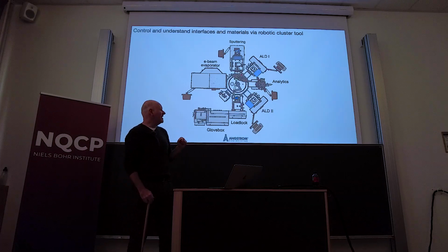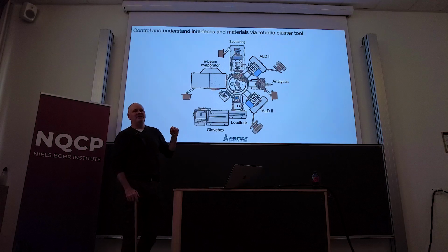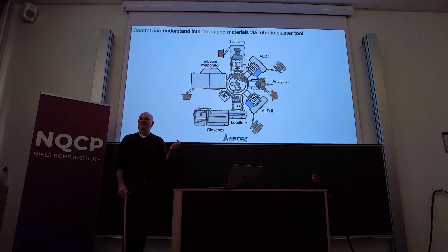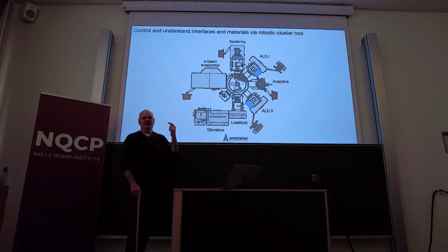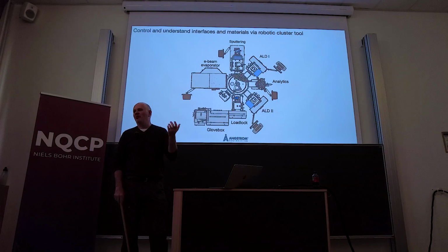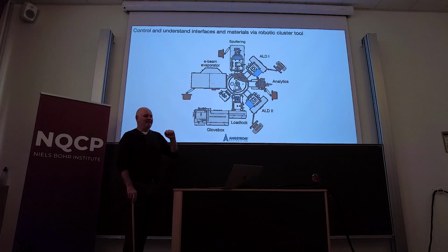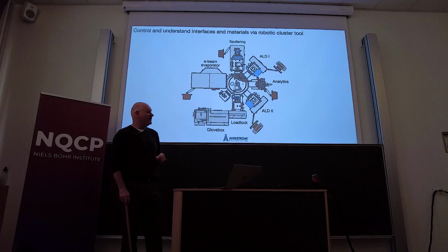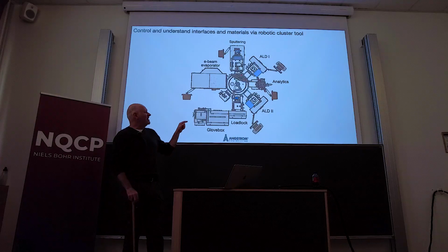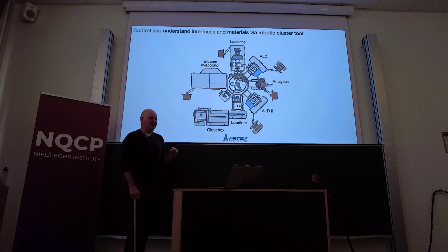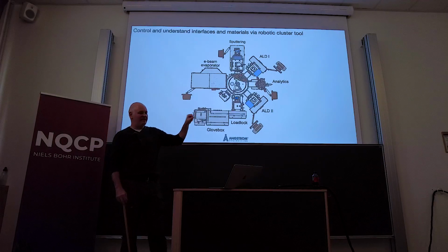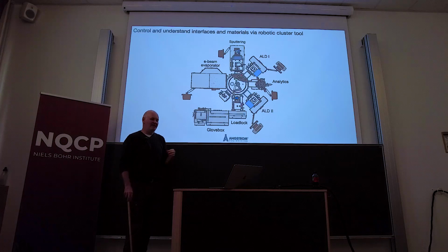The other thing that you can do with an ALD system is you can do atomic layer etch, which is actually the reverse of atomic layer deposition. So you can remove, in this case, about 1 atomic layer at a time, and actually create pristine interfaces, which I'll also talk about in a second. And then finally, there's an analytics chamber on here, which allows us to move the wafer after deposition in, and then carry out things like XPS or ellipsometry, other characterization techniques that can be done in vacuum.